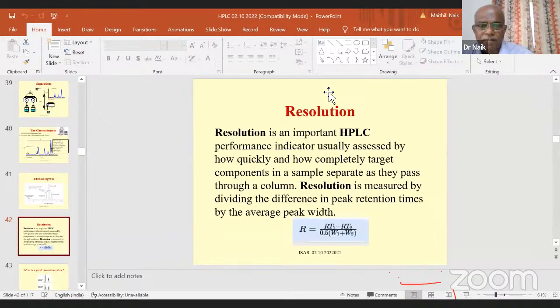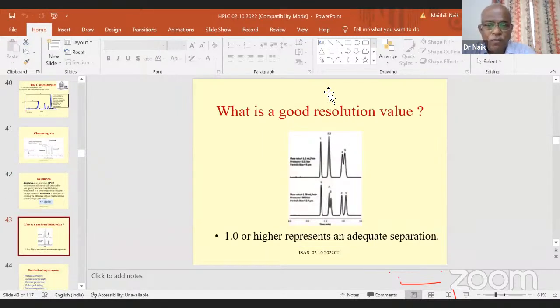And resolution is an important HPLC performance indicator, which is usually assessed by how quickly or how completely the target components in a sample separate as they pass through the column. Resolution is measured by dividing the difference in the peak retention times by the average peak width. This is the formula. What is a good resolution value? You should get a resolution value of 1 or higher, then only we can say the resolution is good.